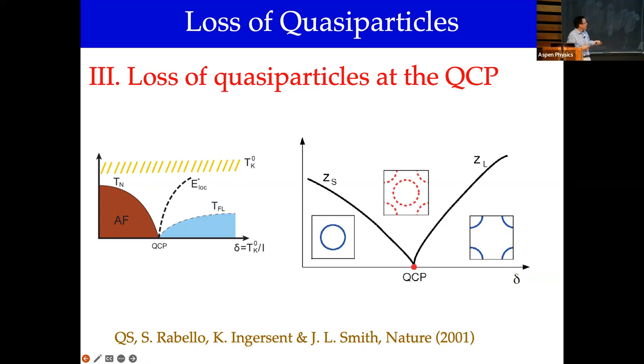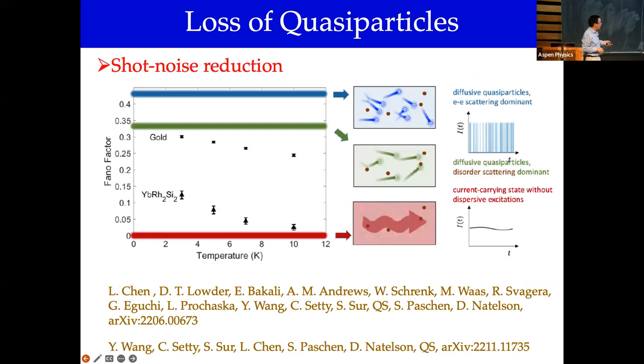The only way for that to happen is that, in fact, if I have a large Fermi surface on which the quasiparticle Z is non-zero in this phase, and I have a small Fermi surface on the left, with a very different volume in this plot, then Z on the small Fermi surface will be non-zero here. You have a Fermi liquid, but as they reach the quantum critical point, the Zs on these two sets of Fermi surfaces have to go to zero in the zero temperature and zero frequency limit. In other words, quasiparticles must be lost entirely on all the Fermi sets, as opposed to the Landau description, where quasiparticles would be lost only on a very small portion of the Fermi surface. Directly testing that experimentally is very hard. There was some thermal conductivity measurement that was done.